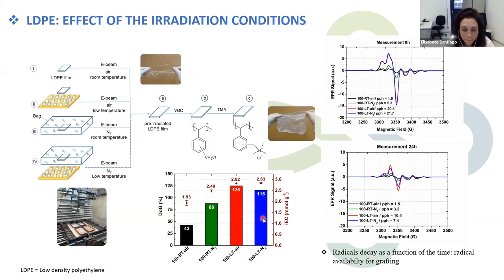So, I mean, low temperature is more significant on the DOG than the atmosphere. So you need the low temperature to achieve higher DOG. There is a reason for that, because the lifetime of the radicals is so short in this kind of polymer. Here you can observe that the radicals decay as a function of time, so low temperature increases the radical availability for grafting. That's the reason.